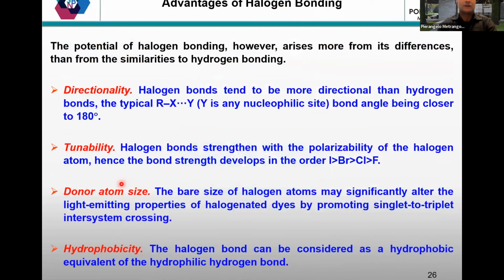And so the reason why I really like halogen bonding is because of its directionality, since halogen bonding always occurs along the extension of the carbon-halogen bond, at an angle which is very close to 180 degrees. It can be easily tuned by reducing the size of the halogen atom from iodine to chlorine, and moreover, the halogen bond doesn't suffer the competition of water. It can be easily done also in water.